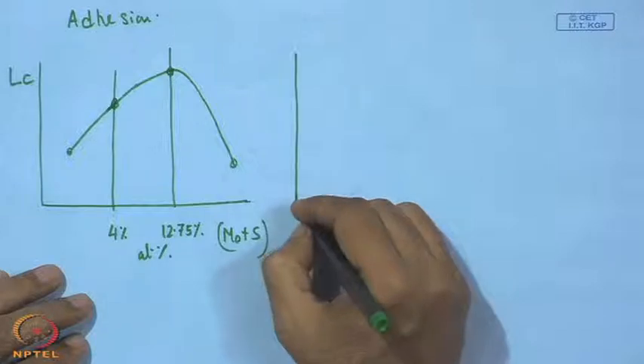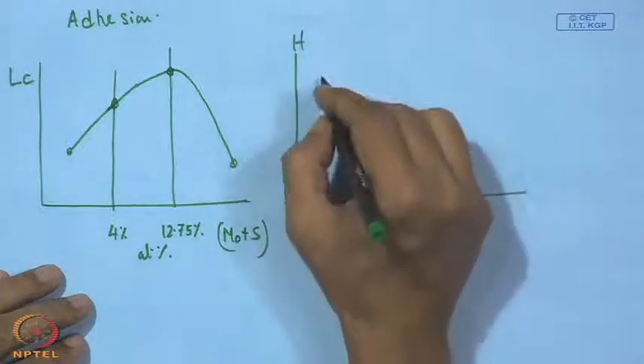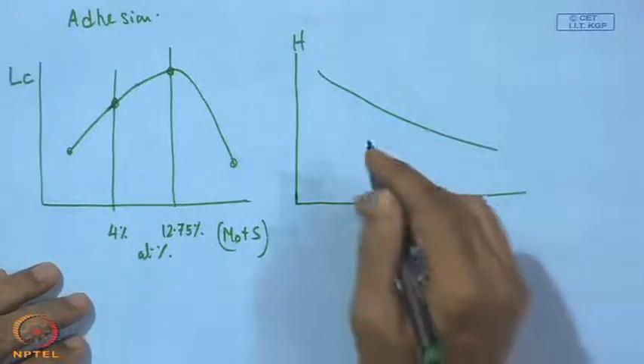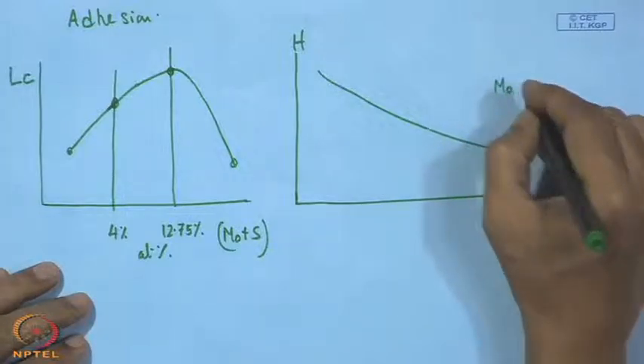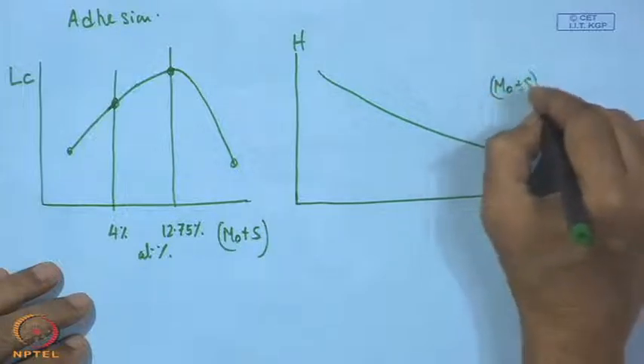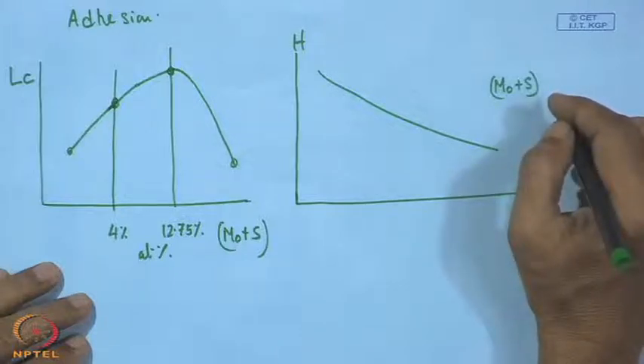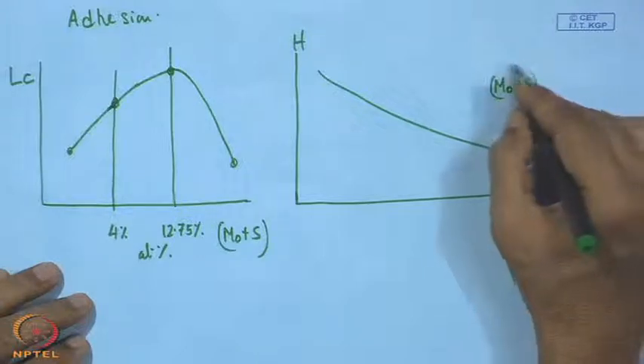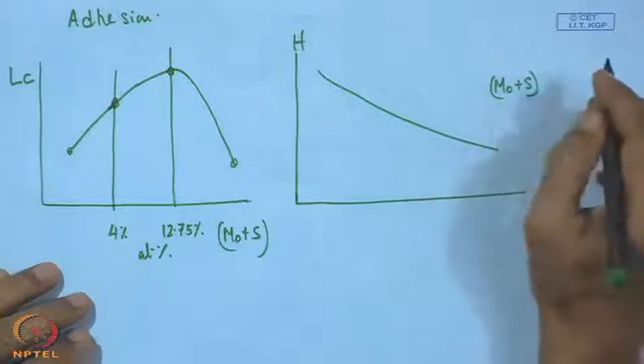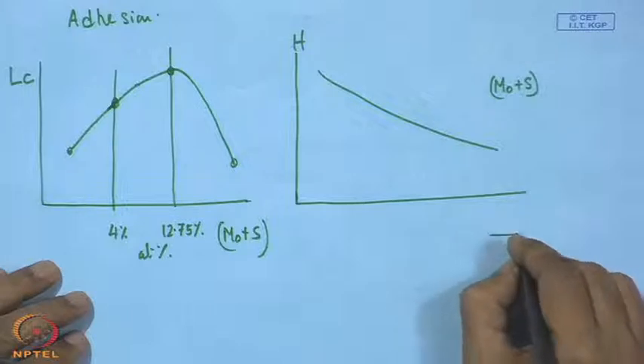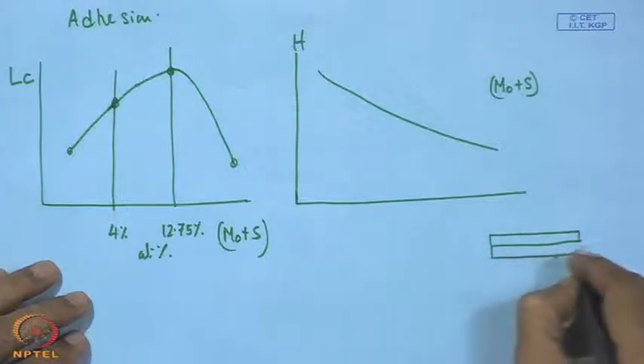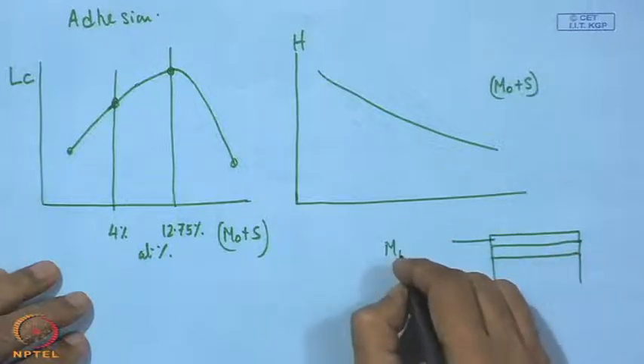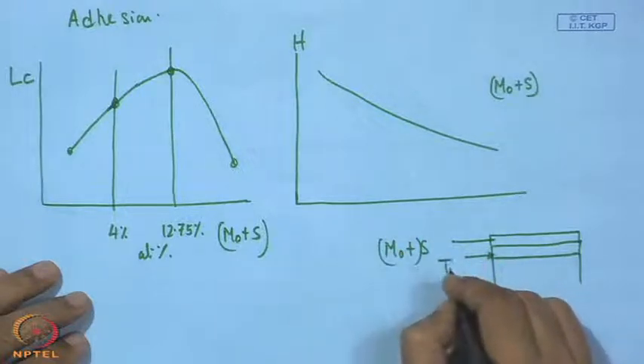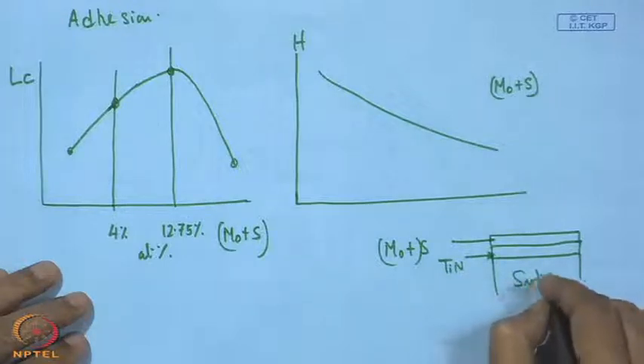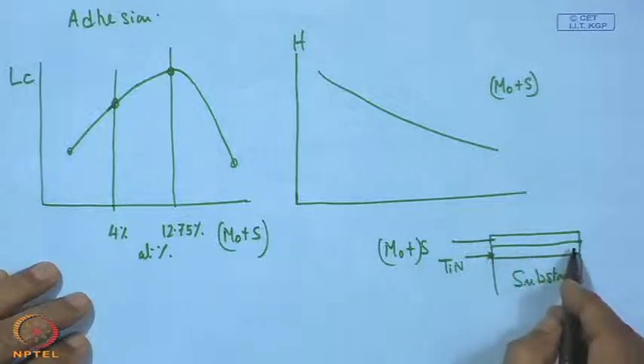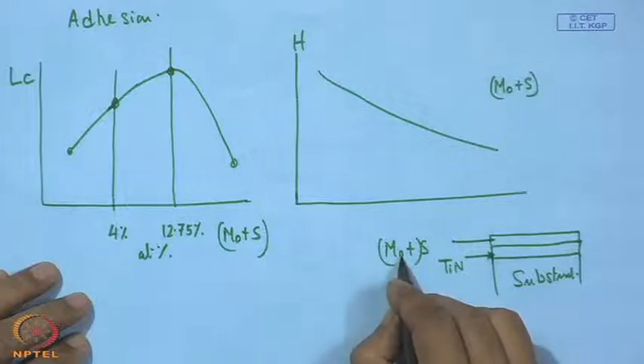However, hardness wise it is continuously falling. The reason is as follows: the higher the percentage of MoS, naturally this is going to be a soft phase, and with this soft phase, the compound hardness, or say the average hardness of this composite structure, falls, because this is going to be a composite structure. Here we have the structure, so this is Mo plus S, and this is titanium nitride. When we measure this hardness, the influence of the substrate definitely comes into the picture, and here we have MoS plus also.